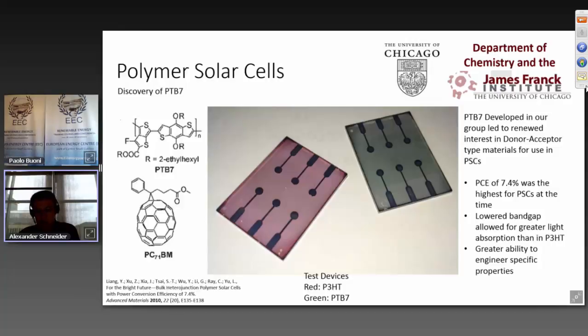Luckily, it turns out that we were able to get higher PCE out of PTB7 than we were able to get from P3HT. And so we increased the PCE of solar cells from the P3HT of about 4.4 all the way to 7.4 in comparing PTB7 to P3HT. And at the time, this was the highest PCE for a polymer solar cell that was known at the time. So this was a very, very big jump in efficiency and very well regarded in the literature. And as you can see, we accomplished this by changing up the structure.